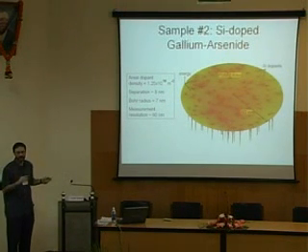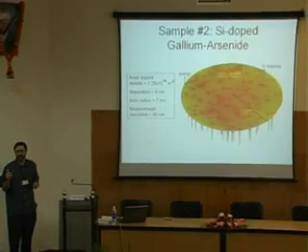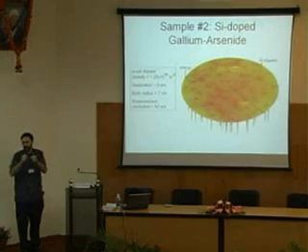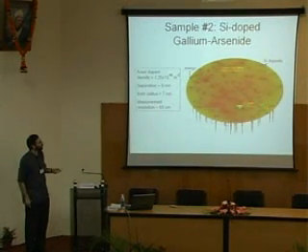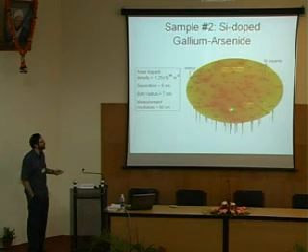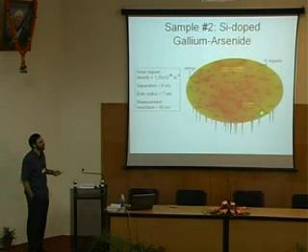The first level of the experiment doesn't say much about interactions, and if we want to do something at least slightly interesting, we could ask, how does the quantum level structure change as your distance to your nearest neighbor changes? That is certainly something you can control with lithography in the future. So we're trying to comment on interactions with nearest neighbors, and it's advantageous that this sample has the neighbors closer together. The big disadvantage is the delta layer is farther away, so that our spatial resolution in this sample is about 60 nanometers. So wherever we put the tip, we're averaging over a big circle.